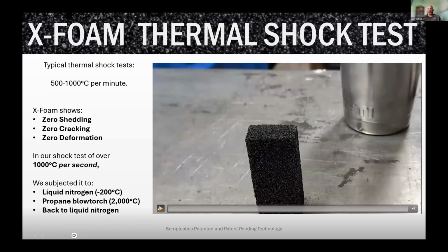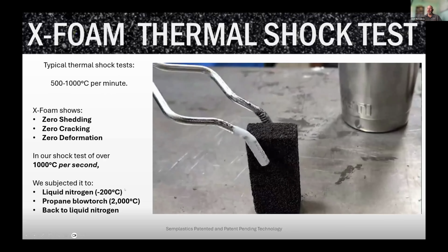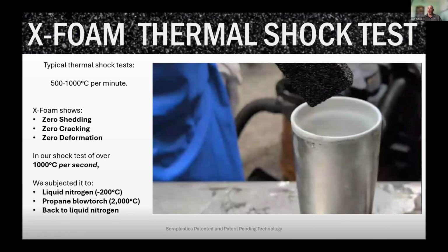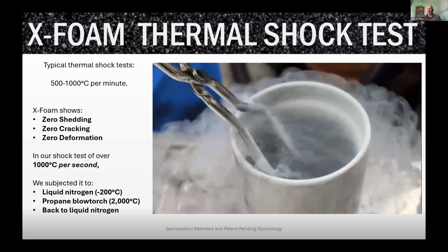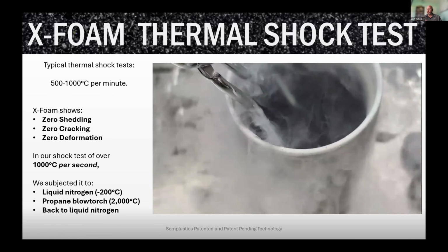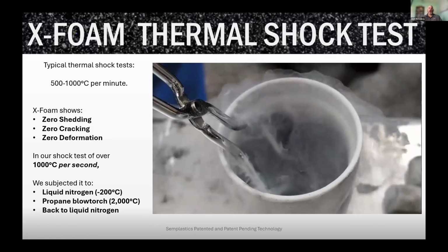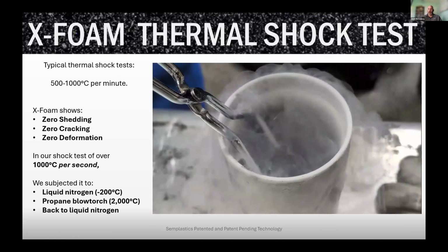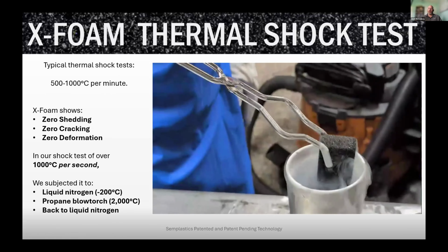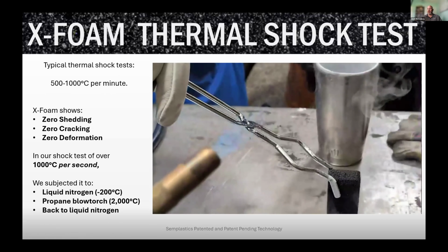Here's something else that's really interesting. On a thermal shock situation, if we take some of this foam and we dip it into liquid nitrogen and let it sit in that liquid nitrogen, just taking it from room temperature, we show that when we dip it into cryo on this thermal shock test, we have 0 shedding, 0 cracking, 0 deformation.